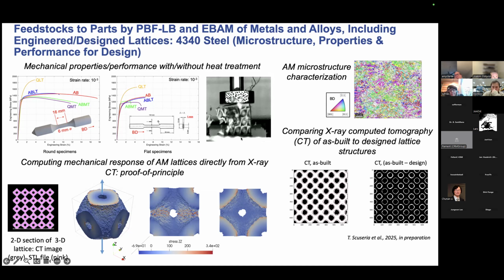High rate mechanical testing, looking at the microstructures we develop with processing and really understanding those processing conditions. We see some unique things in steels that result in maybe some more bainitic or martensitic microstructures that we're trying to deconvolute at the moment. And then understanding, from the topology point of view, what we actually design to build versus what we actually do build with computed tomography, and then forward modeling the properties and performance for these lattice structures.